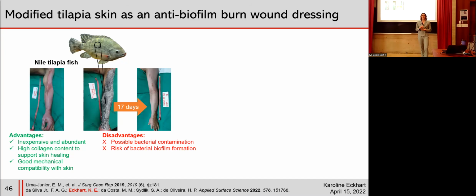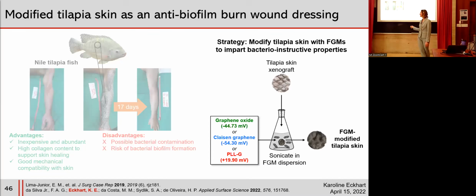A biofilm is very bad. This means bacteria are stuck to the surface, they're proliferating on that surface, and they're laying down an extracellular matrix of proteins and other junk that is making them resistant to antibiotics. So if you have a biofilm, you basically have to remove the implant and try to just decontaminate as much as possible. So our approach was to modify tilapia skin with these FGMs to impart bacterioinstructive properties. Can we control bacterial adhesion on the xenograft using the FGM?